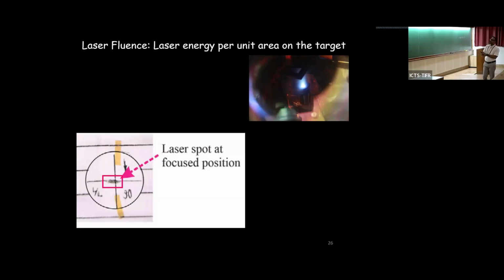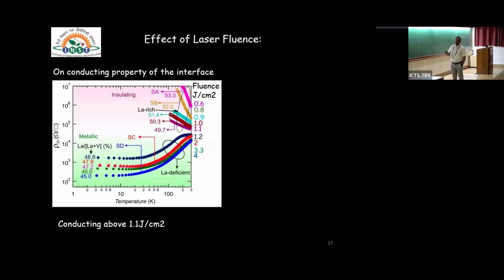We define laser fluence as laser energy per unit area on the target. If you measure the energy and take the area of the laser spot, then you can calculate the laser fluence on your target. What we have done is prepare samples of lanthanum vanadate on top of strontium titanate, looking into the interface, using various laser fluences starting from 0.6 and going up to 4 joule per centimeter squared. When the laser fluence is small, below 1.1 joule per centimeter squared, it is insulating in nature: with decreasing temperature, the resistance increases. But when it is higher than 1.1, that is 1.2 onwards, it becomes conducting, and it doesn't change much with increasing fluence.